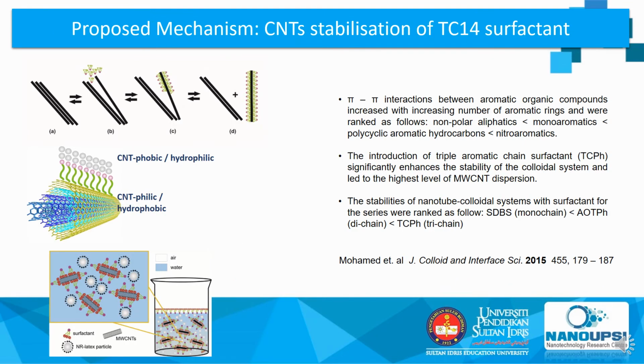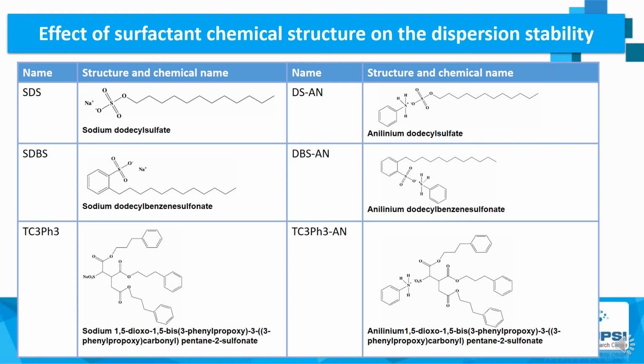latex. And we believe that increasing the phenylsulfonyl group increases the pi-pi interactions between the surfactant chain and the carbon nanotube and helps stabilize the carbon nanotube in the natural rubber latex structures. And in this project, we did a similar concept where we again cross-compare TC3PH3 with the commercially available SDS and SDBS, and in order to increase the number of phenyl groups, we counter ion exchange